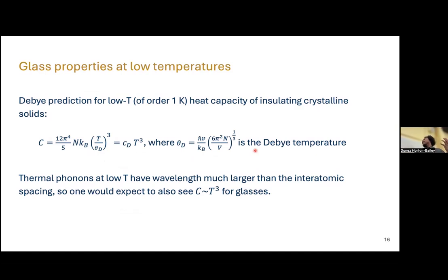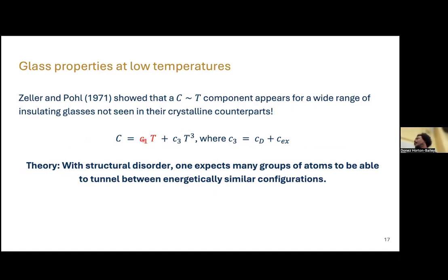This leads to a lot of properties where we can actually see whether we have a glass versus a crystal. One of the things that we see is in the heat capacity of materials. So if you take a solid state physics class, you're going to learn about heat capacity. Heat capacity is the idea that if you add energy to a system, the temperature of that system is going to increase, and the heat capacity is the ratio of that change. For insulating materials like glass, typically or non-glass, you have a heat capacity that depends as T cubed, meaning if you plot T cubed versus heat capacity, you get a line. But for glasses, we actually don't see this. We actually see a linear term. We get this extra T term, and I'll show some plots where this is going to actually make a difference. So this red term here only occurs in glassy materials, only in disordered amorphous materials. You don't see this in crystals.